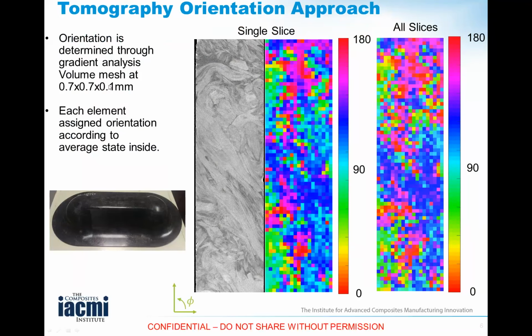In this case, we are showing results for 0.7 by 0.7 by 0.1 millimeter voxel size. The reason we chose 0.1 millimeters is that the platelet thickness is usually between 50 microns to 200 microns, so this falls in the middle. And the color pixels represent the orientation at a given plane, but now integrating the 3-dimensional effect through the thickness, which you cannot see just from the surface.